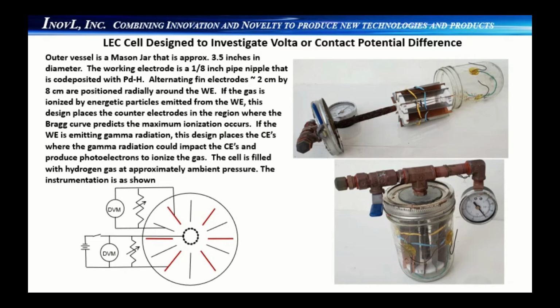It's also possible that if the working electrode produces gamma radiation, that could impact the electrodes and produce a photoelectric effect. As you can see, the cell is basically designed and made from a mason jar about 3.5 inches in diameter. The working electrode is a 1/8 inch pipe nipple that is co-deposited with palladium and hydrogen.